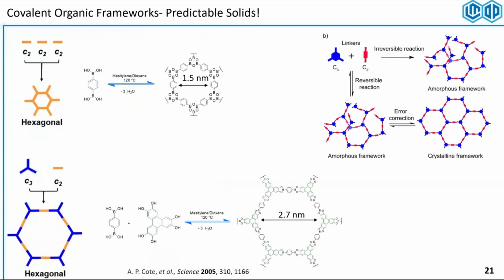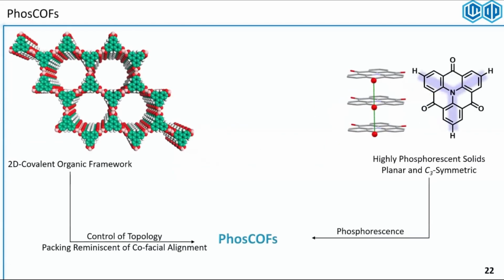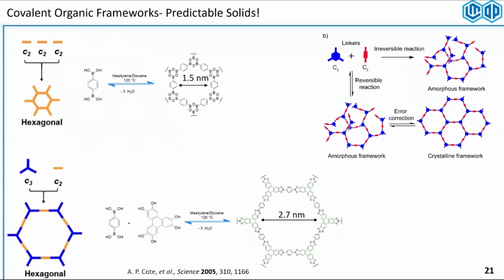And the most important, essentially, trait of making a covalent organic framework is to use reversible linkages. Because if we take normally a symmetric molecule or two and we try to react them, what we end up with, if we have an irreversible reaction, is just a messy polymer, non-crystalline, amorphous, right? We still don't know what sort of molecular interactions are there. Is there pi-pi stacking? Is there not? But if we use reversible reactions, what happens is this amorphous phase that forms will do exchange reversibly until it does a lot of error correcting mechanisms to generate a crystalline framework as the most thermodynamically stable phase for these compounds.